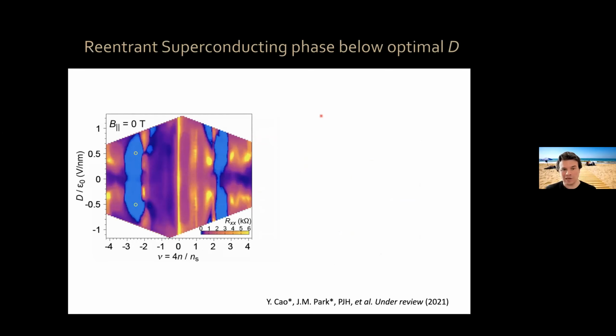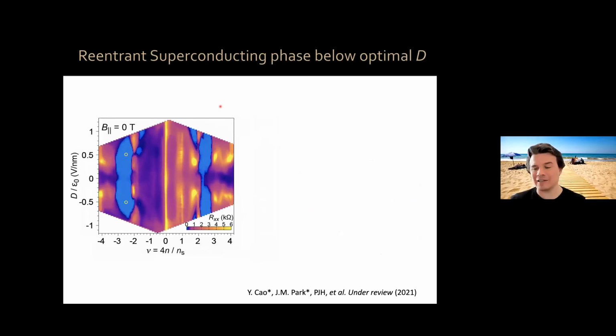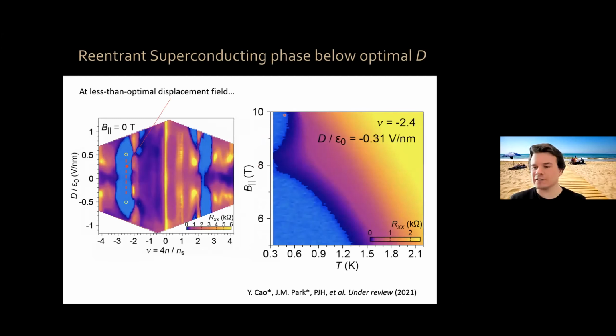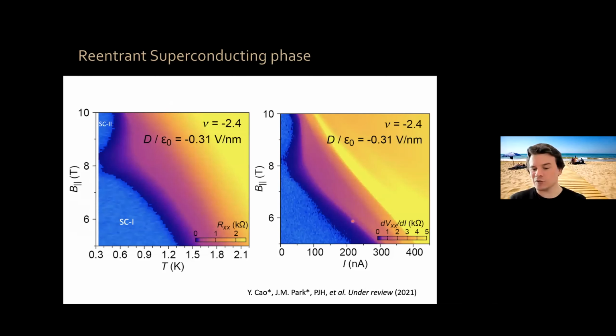Now, in the last couple of minutes, I want to tell you about another behavior that we see, which is very anomalous. The data that I showed you were at optimal electric field and optimal density. If we measure at smaller displacement fields, what we see is re-entrant superconductivity at high magnetic field. This is showing only data in the high field region. You kill superconductivity, and then once you've killed it, it reappears at higher magnetic field. We call these superconducting 1 and superconducting 2 regions. You can do this also in critical current measurements, and this is extremely strange.